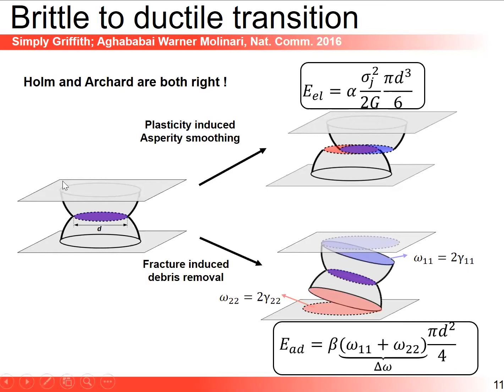So the model is very simple. It's basically a Griffith fracture mechanics approach. We take a very simple geometry of two hemispherical asperities, establishing a junction of size D. As you load your system in shear, you're going to store elastic energy in the system. It's proportional to the elastic energy density.